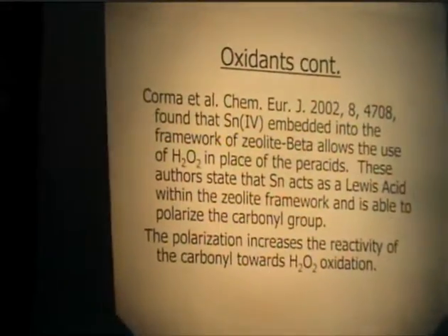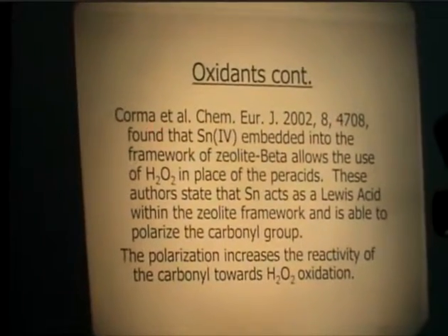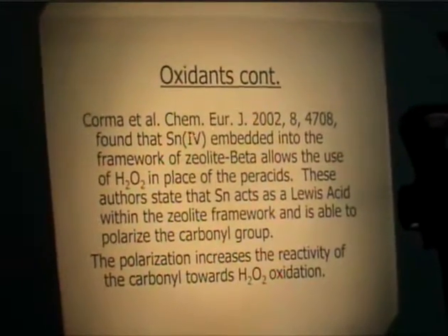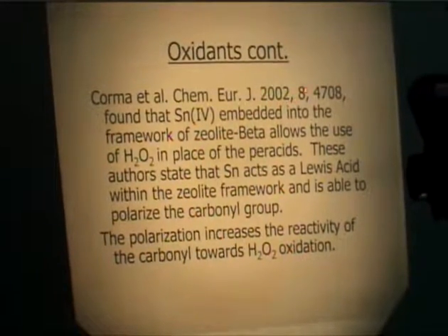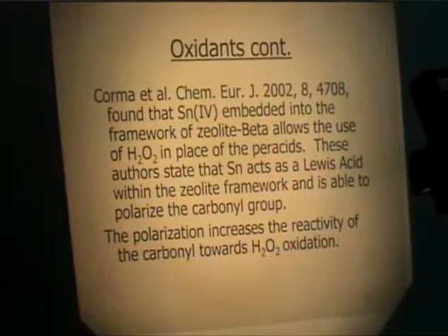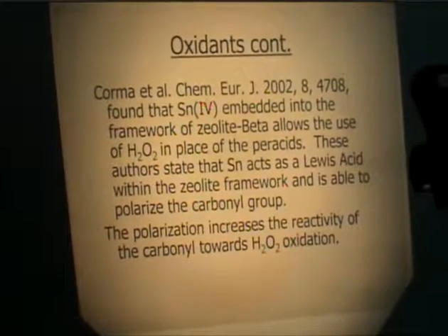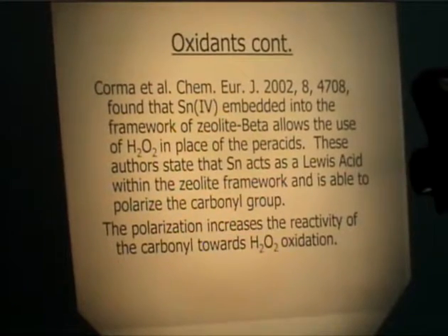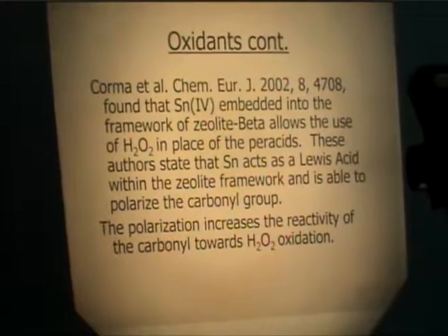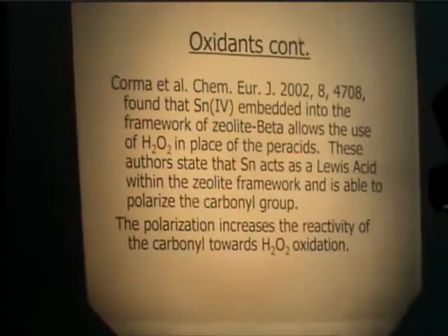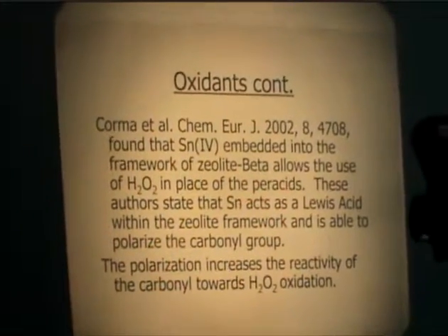Now, here's the interesting thing. I hope it's interesting. Corma published a paper in the Chemistry European Journal in 2002 that he found that tin-4 embedded in a zeolite, in the framework of the zeolite, not in the ion exchange sites, in the framework, allows the use of hydrogen peroxide in place of per-acids.